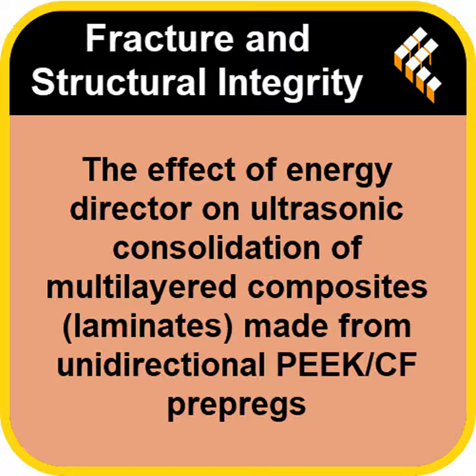That duration gave them an impressive ILSS of over 50 MPa, while drastically minimizing the damaging effects of the vibration and keeping the structure uniform. It's the optimal balance of speed, strength, and integrity. So what does this tell us about the future of this rapid manufacturing technique? The final synthesis is pretty much a clear rejection of these conventional aids. Absolutely. The takeaway is that the approach without the energy director is recommended for making these PEEK/CF laminates.